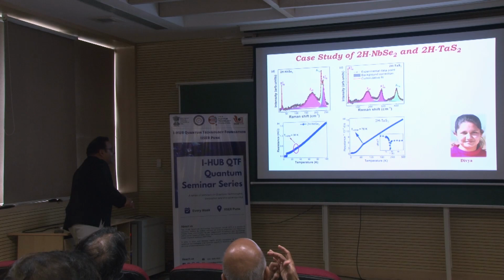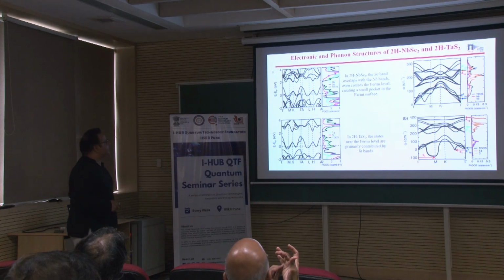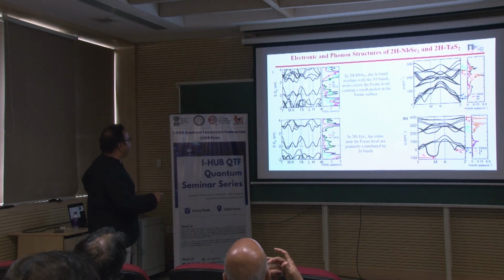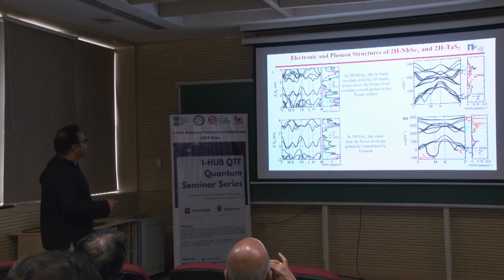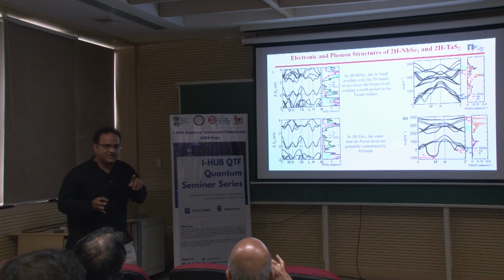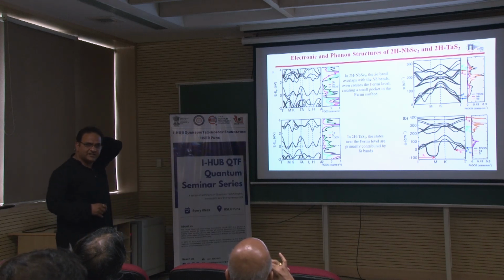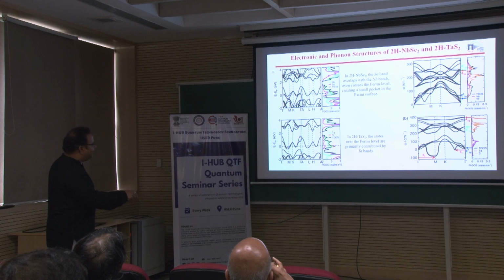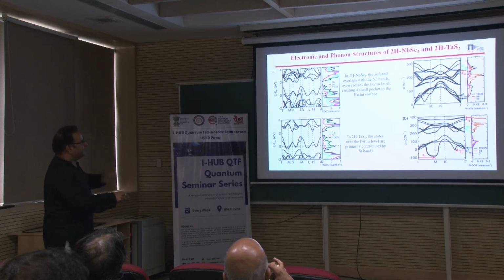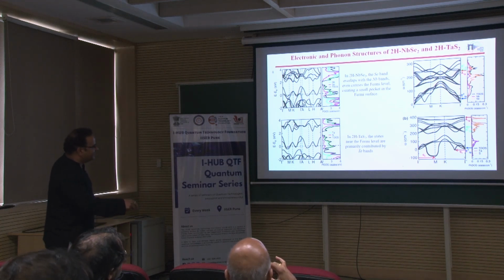and let me just give one line here. Between niobium selenide and tantalum sulfide, in niobium selenide the selenium bands overlap with the niobium bands, even crossing the Fermi level. So you have a pocket in the case of niobium selenide, that is why the superconductivity is there, but this is not there in tantalum sulfide. Here the phonon dispersion is clean and you do not have an instability here, but if you look here at the Q1 and Q2, there are 2 vectors.